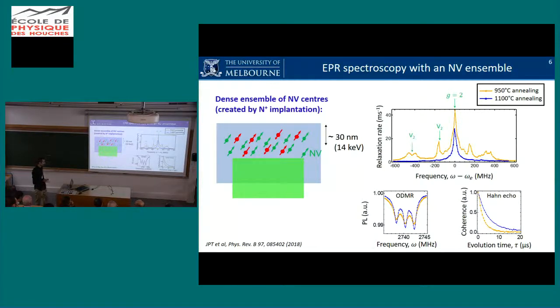So that's an interesting point. It's pretty much 100 megahertz here, and that means those paramagnetic species are very short-lived, so 10 nanoseconds. And that's consistent with what you see also in EPR line width for this kind of sample. So that shows that unlike the P1, which is very narrow, in those kind of samples you don't even see the P1, because all the spins that we detect here are very short-lived.